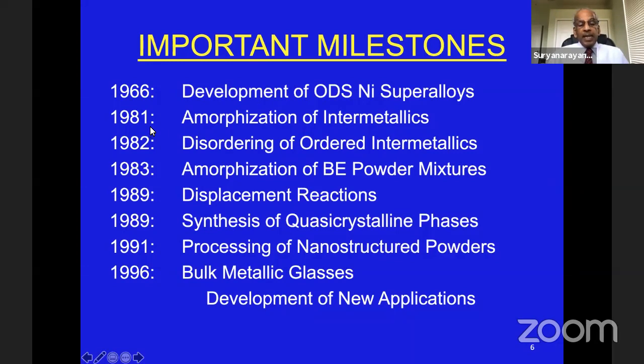But then in 1981, a Russian scientist showed that intermetallic compounds, if you subject them to mechanical alloying, they get amorphous. This was interesting. In 1982, the ordered intermetallics under the influence of mechanical alloying were shown to be disordered, because disordering also has certain advantages. In 1983, instead of intermetallics, one could use blended elemental powders, and those mixtures can also become amorphous. This was shown in 1983.